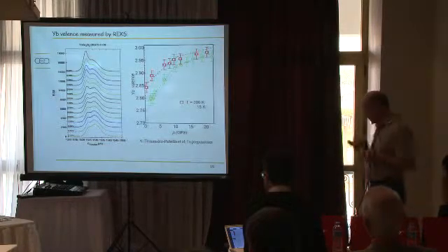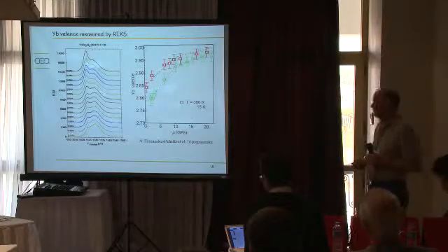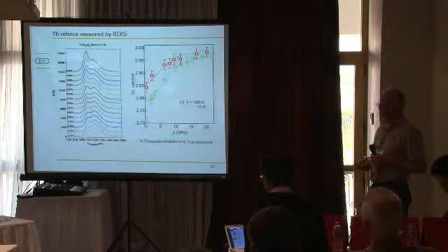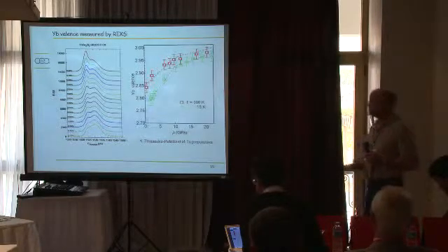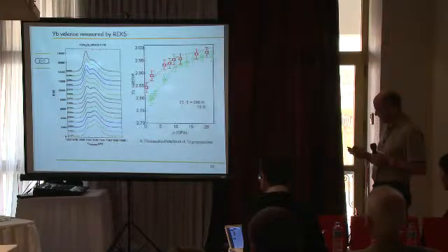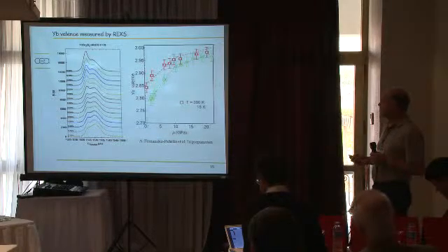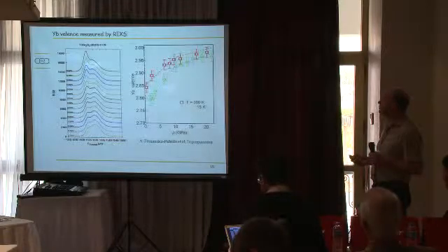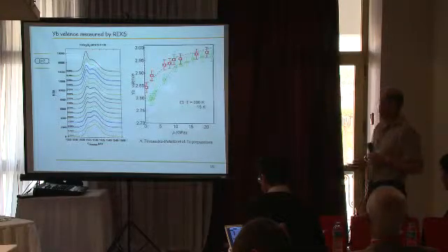Now, from the introduction, you can guess that what I'd like to know is what the valence is doing across this phase diagram, and this we've been able to measure recently using resonant inelastic X-ray emission at ESRF under pressure and at low temperature. And what we see is that the valence increases with pressure, going towards the Yb 3+ state, and there is a pronounced kink which occurs close to the critical pressure, and this kink is actually more pronounced at low temperature.